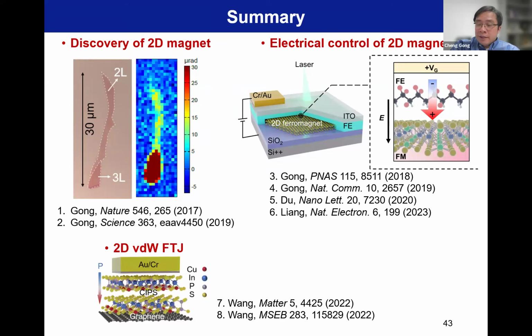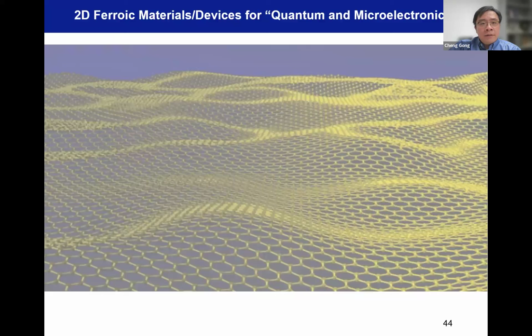Finally, I talked about a device work based on 2D van der Waals ferroelectric materials, and we built such a ferroelectric tunnel junction. Due to the three enabling physics I just reviewed, we achieved a record high on-off ratio of 10 to the 10 at room temperature, four orders of magnitude higher than the best on-off ratio in the traditional oxide ferroelectric based FTJ.